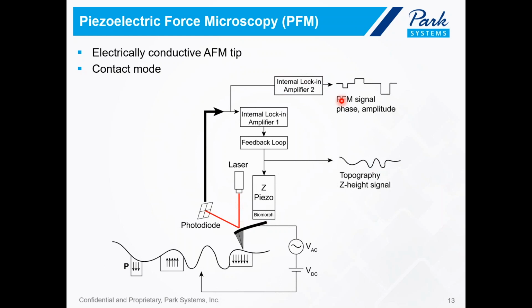So a second lock-in amplifier is connected to the deflection signal to selectively drive the desired AC frequency and bypass the unwanted signals. So PFM phase and amplitude signals are acquired and can provide us the information about the direction of the electrical polarization and also the strain.